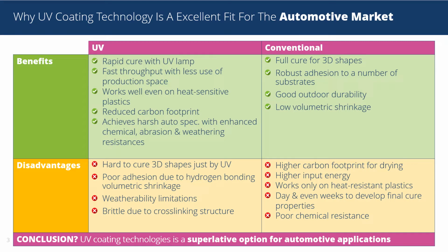Conventional coatings have served the automotive market well for many decades, offering full cure of a variety of geometric shapes, excellent adhesion to a multitude of substrates, and outstanding durability. The process for curing conventional chemistries comes at a cost. Unlike UV, conventional coatings do not cure in a blink of an eye. They require a large carbon footprint for drying and curing. That process typically requires a thermal step greater than 100 degrees C and for a minimum of 15 minutes. And that's just to develop the green strength. Such temperatures limit the number of substrates available to designers.